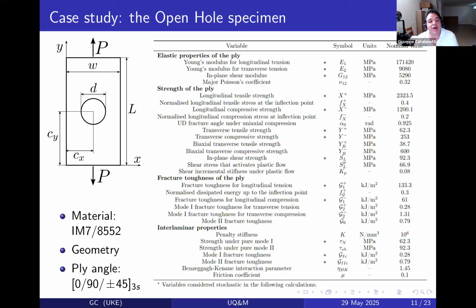Now, what are the variables that you can consider stochastic? Several. All these variables here that contain elastic properties, strength, fracture toughnesses, interlaminar properties are all parameters that I put in my model. Some of these are calculated because they depend on other parameters, like in situ strength, for example. They also depend on the thickness of the ply. Others might be assumed to be stochastic.